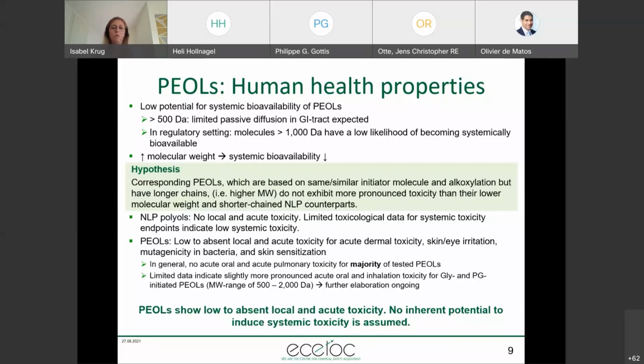But always keep in mind that systemic bioavailability per se does not automatically translate into systemic toxicity. So even though the NLP polyols and lower molecular weight pools have the potential to become systemically bioavailable and reach cellular targets in the organism, this does not automatically mean that any toxicity is observed. So for the NLP polyols, no local and acute systemic toxicity was observed. Also, limited toxicological data for repeated dose toxicity indicate low systemic toxicity, in most cases even up to the limit dose.